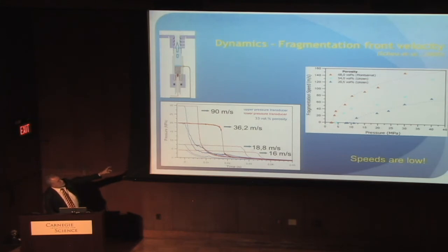If you look at this plot, it's the speed of the process. How do we do that? We have dynamic pressure sensors. You can see up in the high left-hand side. You have a dynamic pressure sensor above the sample and one below the sample. So we're simply measuring pressure over time above and below the sample. And the time between the decompression hitting the top of the sample, which we see in the first sensor, and the decompression hitting the bottom of the sample, which we see in the second sensor, is the time it takes to evacuate that sample out of the tube. That's a simple approximation.